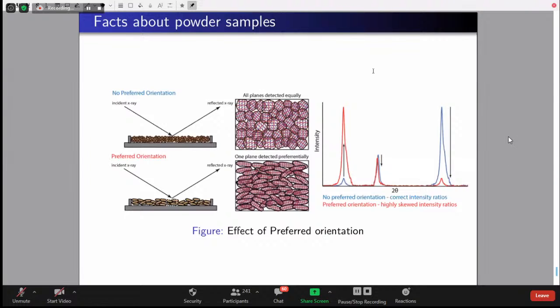Some samples are there which grow preferably in one particular direction. For them, nothing can be done. But usually for powders, you should grind it properly and measure it. If you have doubt of preferred orientation, my suggestion is just as I told you, turn the sample 90 degrees in one more direction, measure it again. Then obviously if there is an intensity change, you will know that your sample is having preferred orientation.